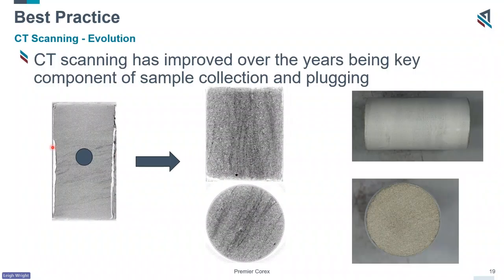And again, we're going back to this whole sample here. You can see that we take the plug from there. You can then see that it's been correctly orientated. You can see a nice PTFE wrapped sample. But again, with the higher resolution, we can now see that if we were to move this slightly over to the side and take multiple samples from these different areas, you know that you're capturing samples from the same zone. And we'll talk a little bit about that in the formation damage example I have later on, where we've got real life examples of a study that was done. But making sure that you're getting the brother and sister samples correct.